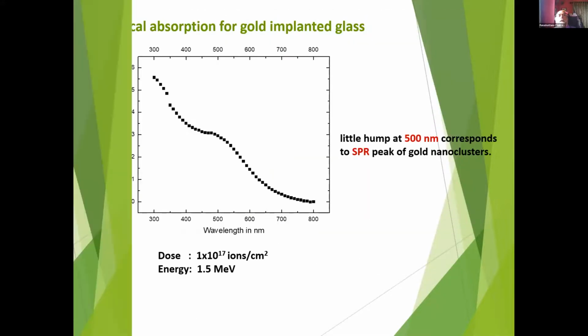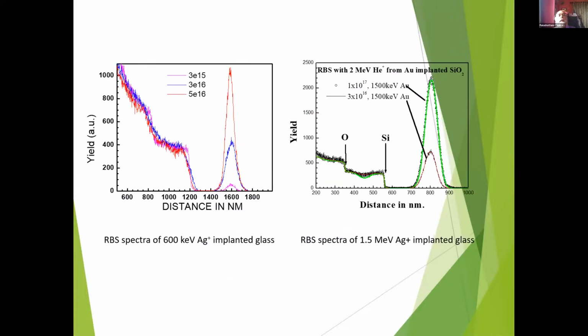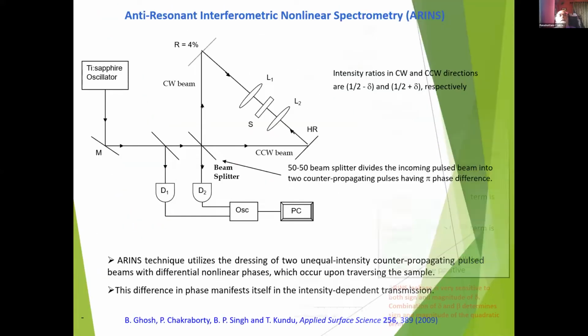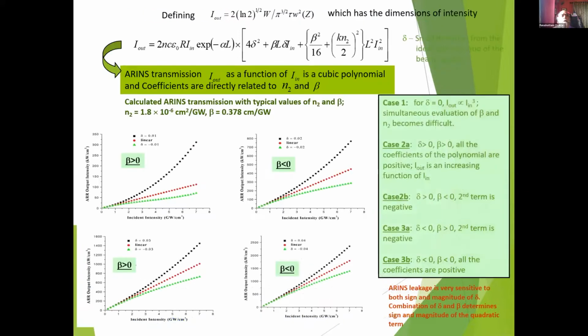Now I would quickly go on to say that we are getting the nonlinear optical responses of these by a new technique which we have devised, called anti-resonant interferometric nonlinear spectroscopy. This is a very new kind of experimental setup which we have developed in our laboratory, and by this technique we measure the ARINS signal, which gives a nonlinear phenomenon. The nonlinearity in the ARINS signal as a function of incident intensity gives you the signature of the nonlinear refractive index.